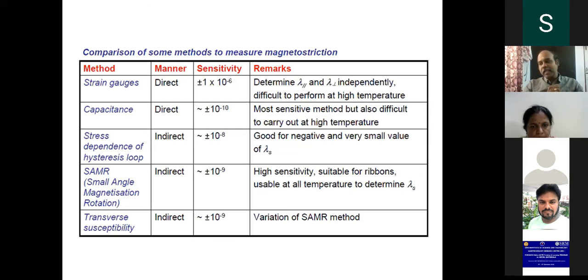The next thing is a capacitance bridge. In a parallel plate capacitor, as the distance between the plates changes, C is equal to A epsilon naught by d, so the capacitance is going to change, and that is also a technique for finding the magnetostriction. The third one is the strain-based hysteresis loop. That is, you apply a stress and you see how the magnetic loops change. You can also use small angle magnetization rotation, which is very sensitive but very complex to do. We can also measure the transverse susceptibility, which is an indirect technique to measure the magnetostriction. But conventionally, the first 2 techniques, the strain gauge technique and the capacitance technique, are mostly used for measuring the magnetostriction.